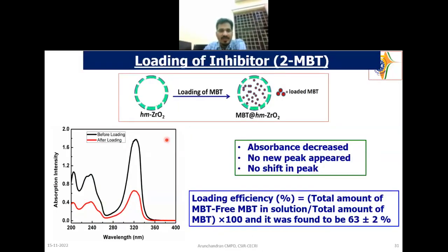And later we loaded this zirconia using MBT inhibitor. This is post loading only, and this is how you can confirm the loading. Before and after loading, we take the UV intensity of the inhibitor solution. After loading, we found that the intensity was reduced, so assuming that the lost amount is actually inside the containers. We found that the loading efficiency was about 63 plus or minus 2, because we duplicated all the experiments and found out the error value also here.